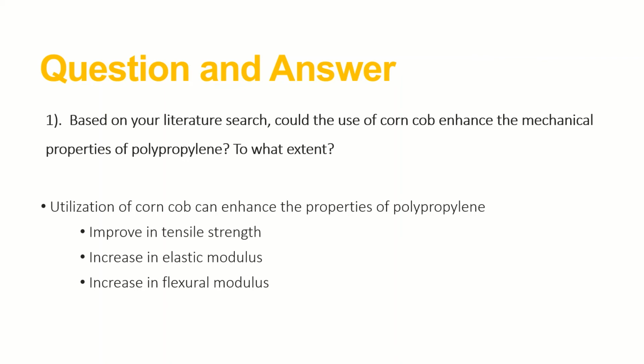In the study conducted by Onuwawa et al. in 2017 and Gunawan et al. in 2021, their obtained results showed that addition of corncob filler in the polymer matrix improved the tensile strength of the resulting composite. And this may be attributed to the fair distribution of the filler, which hinders chain movement during deformation, as well as the strengthening effect of the filler into the matrix.